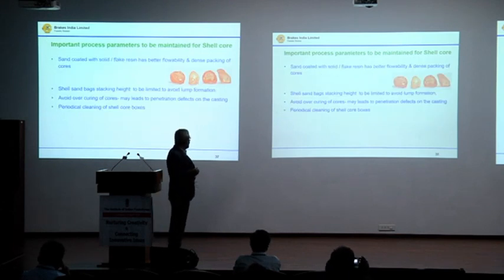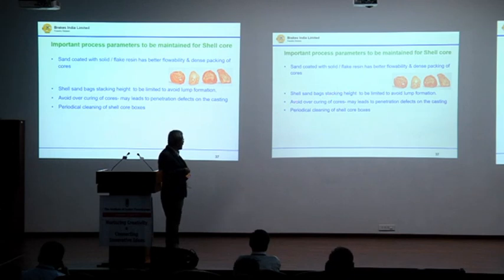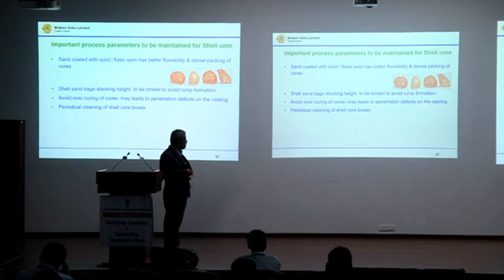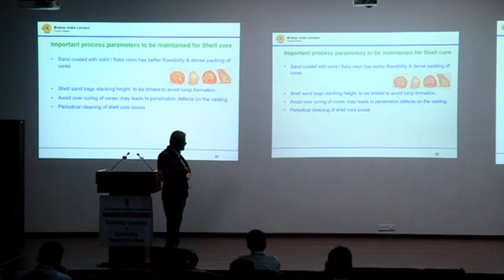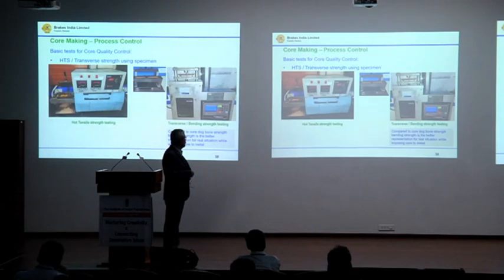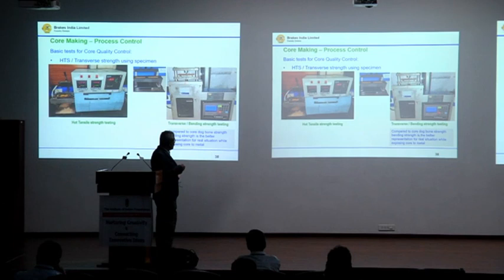So sand coated with a solid flake resin is better for flowability and dense packing of cores. Shell sand bag stacking height should be limited to avoid core lump formation. Avoid over-curing of cores, as it may lead to penetration defects on the castings. Periodical cleaning of core boxes is needed to avoid resin buildup affecting dimensional accuracy. So for shell cores, we do hot tensile strength and transverse strength tests.